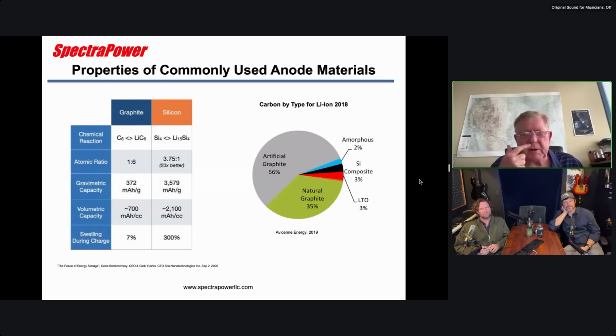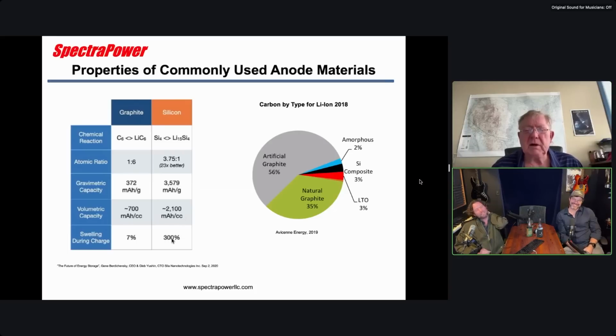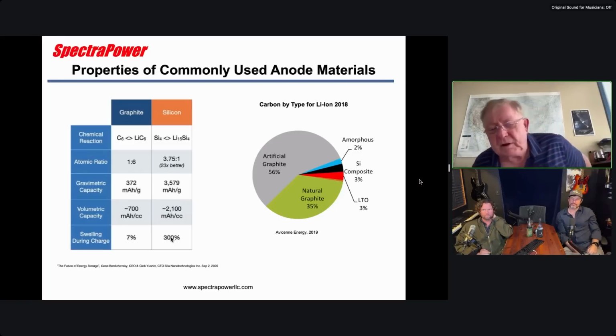And people don't typically see that because it's made up for in the cell design. But graphite will take up to a certain amount volumetrically, and it will swell while it's doing it. 7% is a pretty typical number. So on the silicon side, you can get much higher capacities. It will take up a lot more lithium, but it's going to swell. Three times the size. Jeez. Yeah. If you try to lithiate, it can actually go up to more like 400%. If you fully lithiate silicon, your cell will actually burst open because the volumetric increase is so large.